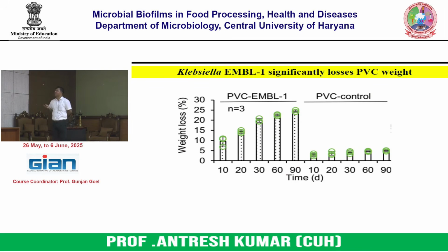They have measured the weight. This is the control, using a different time period study. They have also grown this particular Klebsiella strain time-dependently. So with respect to time, an approximately 25% loss in the PVC was observed at around 90 days of incubation of these Klebsiella strains.